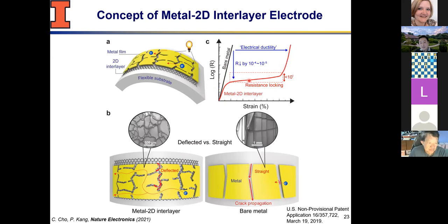And the graphene with the 2D, graphene with the metal, it actually created quite interesting behavior. So here we start to see almost like plasticity, right? There's some, almost as if there's some dislocations working through the material. It's actually not, but it's very similar to that of ductile deformation until you get completely fractured. And this resistance level is really not more than 10 times the original resistance of the metal. So if we start with a few ohms, this is like 10 ohms or less. So actually it's keeping that resistance for a long strain until it breaks. So that was quite bizarre, but that's what we saw.